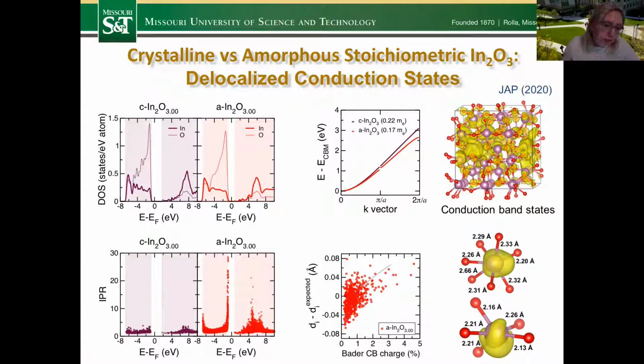And that's why the electronic properties are actually very, very good in these materials. Despite that we have an amorphous phase, because the nearest neighbor indium-oxygen distances are very similar to the crystalline, the overlap is not very much affected, because indium has an s orbital. And this is an ionic material, so the overlap between the oxygen p orbitals and indium s orbitals is not really affected. That's why at the bottom of the conduction band, we have very delocalized states. So at least in the stoichiometric and weakly understoichiometric material, we still have very delocalized states. The only localization occurs at the top of the valence band as we go from the crystalline to amorphous material. But again, the conduction band is very delocalized.